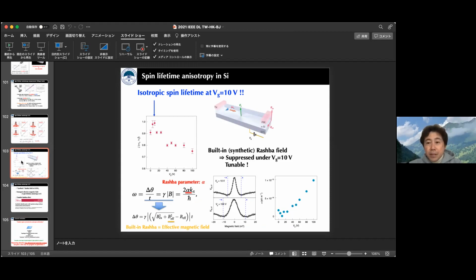Currently, there are two possible interpretations, we believe. The first one is the interface between silicon and SiO2 itself. Because this is a heterointerface, as in the case of bismuth silver or other bilayer systems, the Rashba field definitely exists, and this induces a synthetic Rashba field, an effective magnetic field. This is one interpretation. The other interpretation is the thickness of the silicon channel. In the talk, I did not tell you the effective thickness of the silicon spin channel, but the spin channel thickness is 80 nanometers.